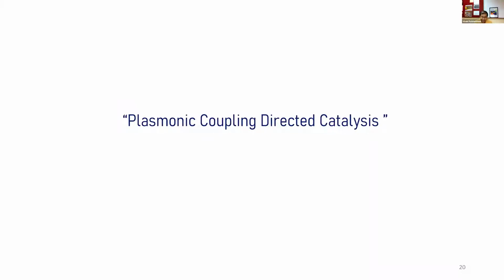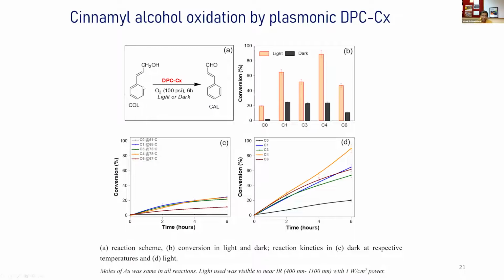So the first, simple reaction that we carried out is alcohol oxidation. So this is the alcohol, and this DPC-Cx is the black gold, dendritic plasmonic colloidosome with different cycles, and oxygen was the oxidant. And you can see now dark versus light. Let us say C4 in dark is around 25%, and in light it is around 90%. So why do you have a better activity in light as compared to dark? The simple answer could be that maybe you have a higher temperature because this electron-phonon coupling produces heat.